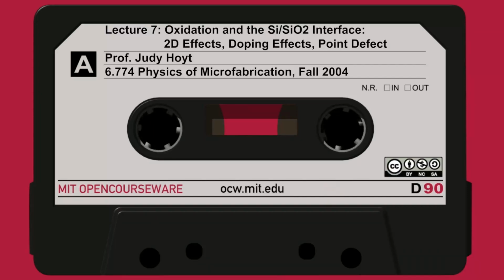And then he took those pillars and put them in the furnace and oxidized them. The idea was he wanted to get the pillar diameter down. He could not lithographically make the pillar any smaller, but he wanted to look at quantum effects, current conduction in this very thin wire. He wanted to get it thinner somehow. And an obvious way to make it thinner is to oxidize it, right? As you oxidize, you will consume from the top and all the way around the sides of the little cylinder, you will consume the silicon by the SiO2 production.